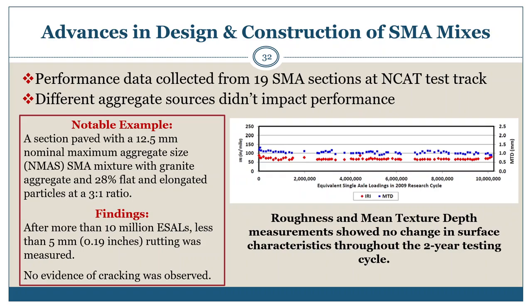Performance data has been collected on 19 SMA sections at the NCAT test track. Different aggregate sources have been used, but that had no significant impact on performance. In the graph shown on the right, the red diamonds are the IRI values in inches per mile measured over cumulative equivalent single axle loads, while the blue squares show the mean texture depth over that same time period. So roughness and mean texture depth measurements showed no change in surface characteristics throughout the 2-year testing cycle of different SMA mixtures that have been designed, constructed, and produced as SMA mixtures.